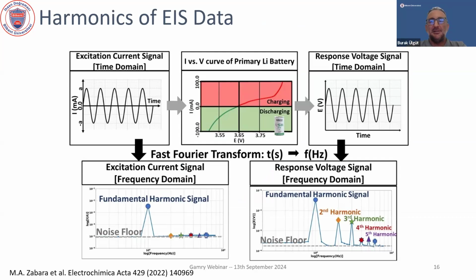So on the impedance side, what this manifests itself as is harmonics. Okay, so if everything is linear, the signal on the voltage when you are applying a current is going to look like what you are seeing on the left-hand side at the bottom there. The only thing you see is the fundamental, and then the higher harmonics are all at the noise floor. This is logarithmic, so there's more than 2 orders of magnitude between these two. And then when you have something nonlinear, you have the fundamental, and then you have a lot of power in the second, third, fourth, fifth, and sixth. And how they order actually tells you something. And the fact that they exist tells you a lot of things in addition to how they are related with each other. Okay.